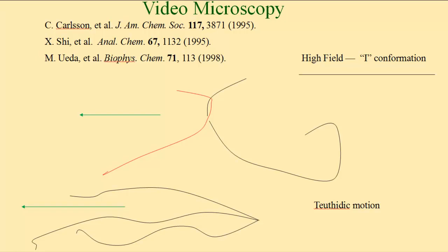At the moment, that red chain has been entangled, is wrapped about the black chain. The red chain is in a configuration described as a J configuration. The chain is advancing to the left, the green arrow. The red chain drags the black chain along. The places where the moving chains and the matrix chains intersect have many of the properties assigned in heavy bead models to heavy beads, with one important exception: the beads are free to migrate along the chain, and indeed, as